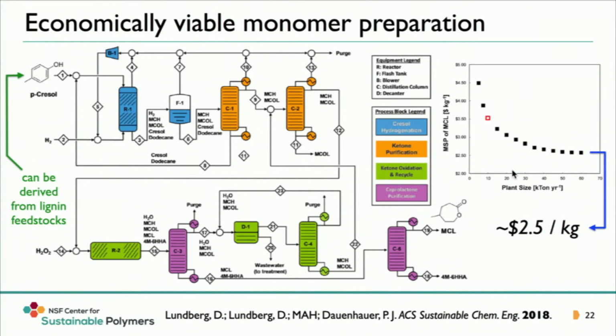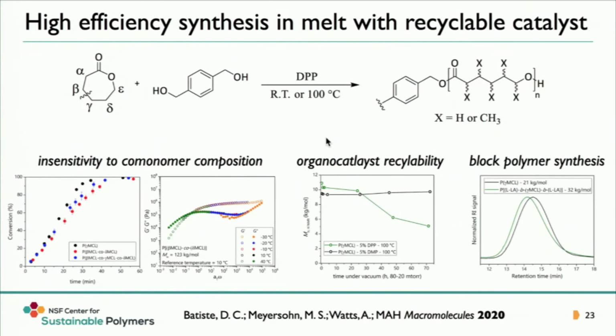So what Derek Battiste has done in my group with those methyl caprolactones, and a variety of them, where alpha, beta, gamma, delta, and epsilon substituted methyl caprolactones can be made, was show that through the action of organocatalysts, in this case diphenyl phosphate, we can highly efficiently convert these into high molecular weight materials. Now, by efficient, I also mean that we can do it in the absence of solvents, at very low levels of catalyst, at relatively moderate temperatures. And what Derek was able to show is that it doesn't really matter where the methyl group is on the cycle, with one exception, the polymerization rates and ultimately the polymer properties are relatively insensitive to comonomer composition.